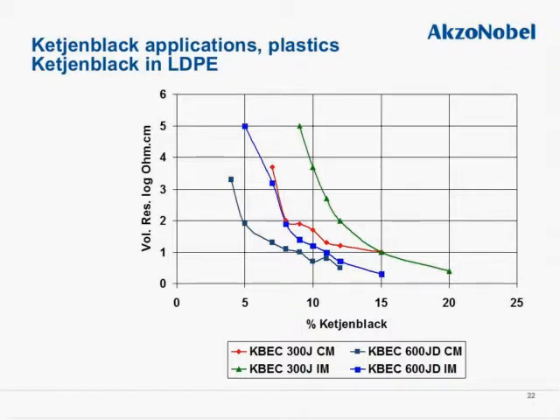Similar example, Ketjenblack in LDPE. Again, comparison of Ketjenblack EC-300J, both compression molded and injection molded, as well as Ketjenblack EC-600JD, also compression molded and injection molded. In this case, we have few data points, starting at about 3% with Ketjenblack EC-600JD and about 5% with Ketjenblack EC-300J. And the data looks a bit scattered only because those are lab samples.